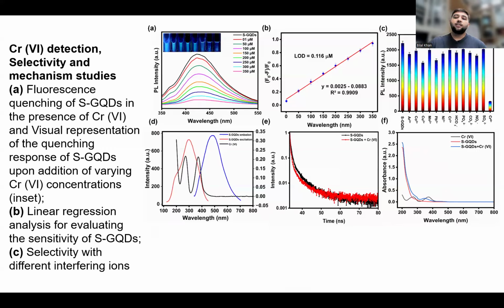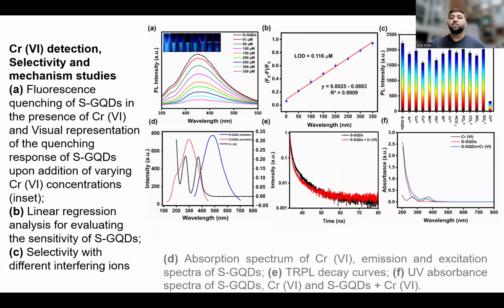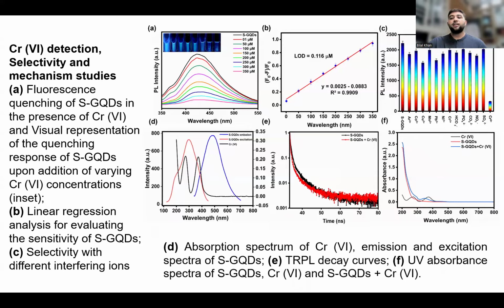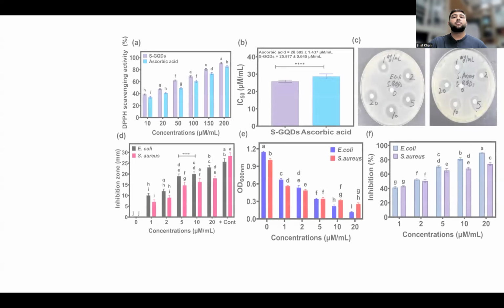We took the absorbance spectra of chromium-6 separately, sulfur-doped graphene quantum dots separately, and also together. In the mixture, we already see the complex formation, and from this we can confirm a static quenching mechanism. So our quenching mechanism was dominantly by IFE, inner filter effect, and secondarily by static quenching.